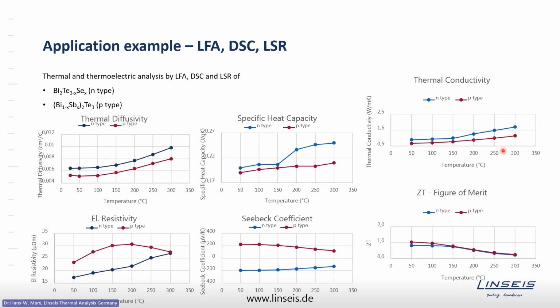And a last example, a full characterization of 2 materials, P and N-type bismuth telluride containing also selenium or antimony, by laser flash analyzer. So this is a representation of the thermal diffusivity over temperature. The specific heat capacity has been measured in the same temperature range. The density is known. So you may calculate the thermal conductivity by multiplying the diffusivity with the specific heat and the density. This has been done by laser flash analyzers, specific heat by DSC machine.